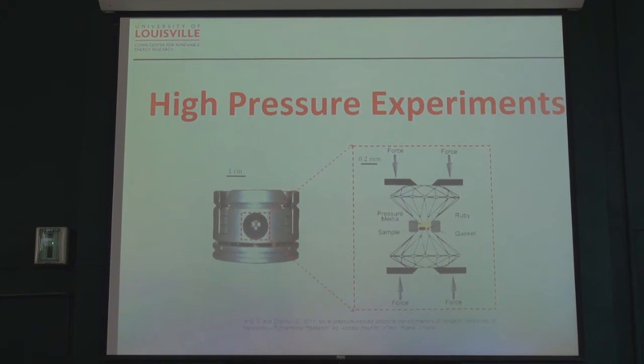Okay. So when you talk about high pressure, we are talking about gigapascal kind of pressure. That means we need to use something called the diamond anvil cell. You have these two diamonds, you put the material here and apply force from both ends, so then you can get pressure up to maybe hundreds of gigapascal.